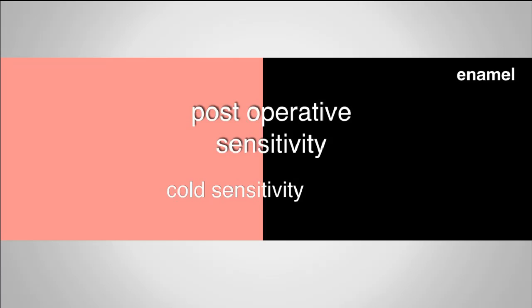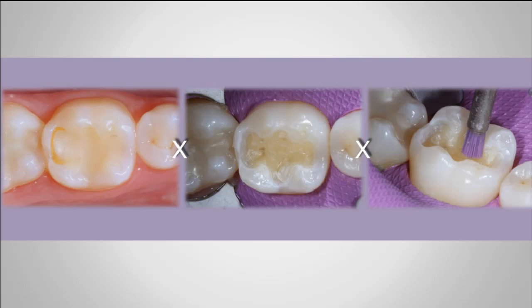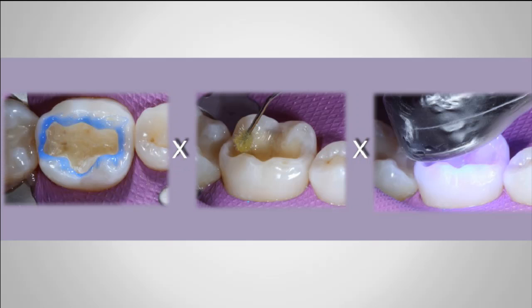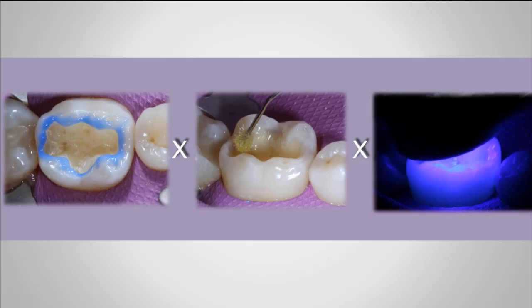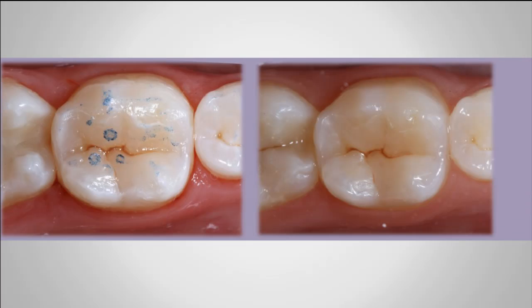The first problem is post-op sensitivity with cold. And this is something that happens after restoration. So when I have this problem, if you see this case, you're going to understand better. I am changing a restoration. I am doing this step by step. I will show you how to do that later, but I'm finishing the restoration, and if you see in the interface of this composite, I can see this white line. Always when you see this white line, it means you have a gap formation. You have an interface. Every time you see some white line around the restoration, this means space.